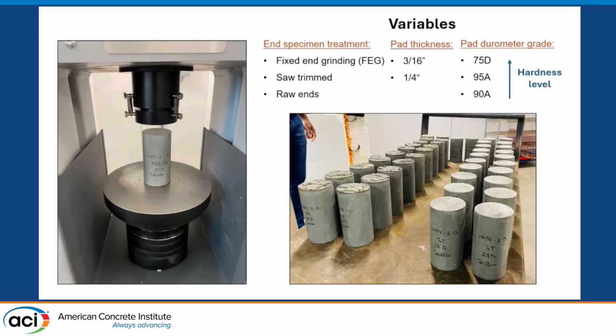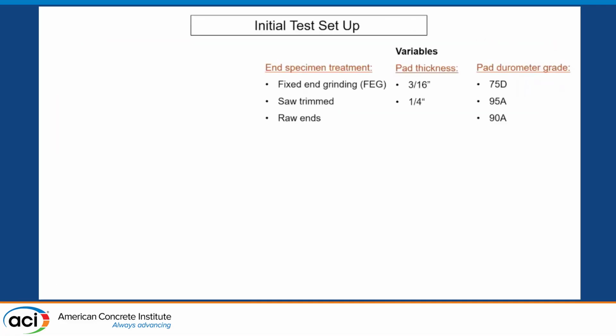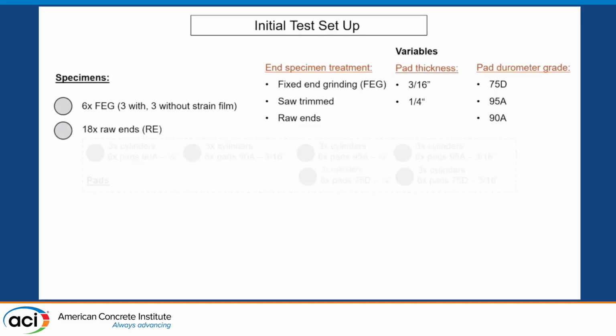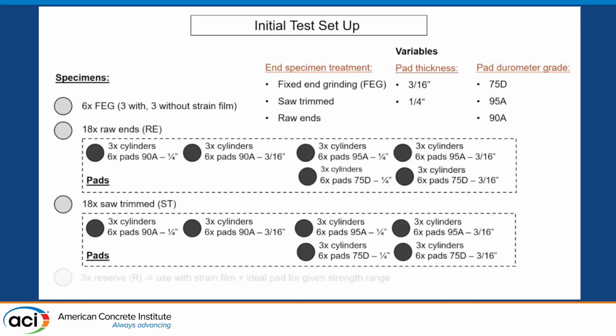So earlier I showed the 70A, which is very soft. 75D in this case represents a very stiff pad. We tested 90A, which is the softest pad in this case, and then the 75D, which is the hardest pad in this case. And this is all based on the durometer hardness scale. And so our test matrix looked a little like this.